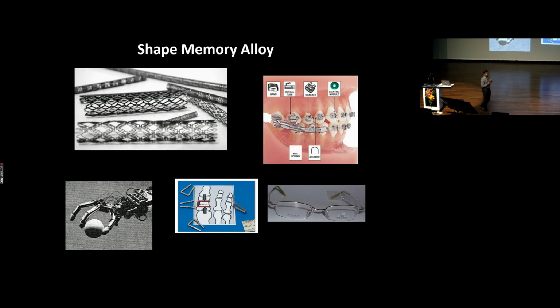For example, if you have an artery that is choking and you need to expand it up, what you do is crimp it down to this narrow tube size so that you can push it through the artery very easily, take it to the right location, and give it the perturbation from outside so that it can open up. Then the artery opens up, which was otherwise blocking the blood flow, saving your life. And this kind of material has this very strange property and many, many applications.